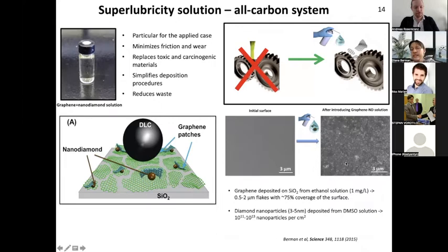That's the whole beauty of this approach of spraying on the surface. From the beginning, when we were developing this, we tried to make sure that we don't need to worry about this perfectness, or about the specific environment conditions for the deposition, because otherwise you are not really seeing the benefit in comparison to just a PVD or CVD coating on the surface. So by spraying and not really controlling what is happening on the surface, it was enough to produce the superlubricity regime. That's why this system is so interesting: during the sliding, it self-adapts, self-rotates to create a better configuration for the tribological system.